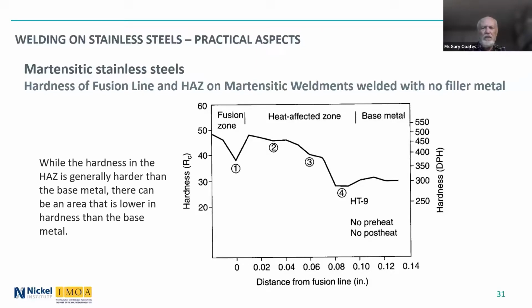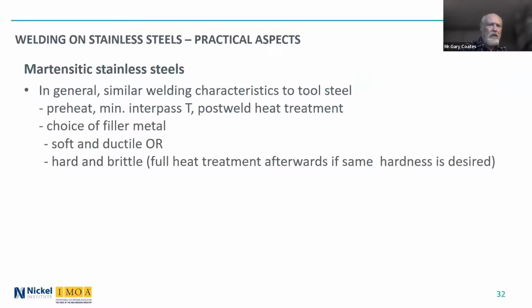But there's even an area that's weaker or less hard than the base material right at the boundary between the heat affected zone and the base metal. So I'm only showing this because welding martensitic stainless steels can be complicated. Very briefly, similar welding characteristics to tool steel as a general statement.